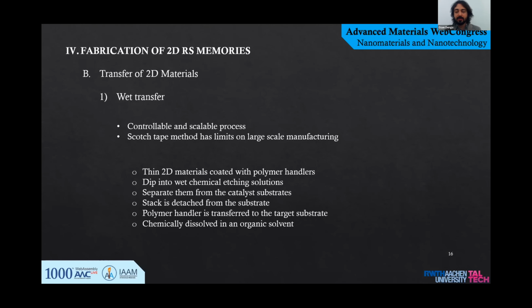But during the wet transfer process, thin 2D materials coated with polymer handlers are dipped into wet chemical etching solutions to separate them from the catalyst substrates. Then, the polymer and 2D material stack is detached from the substrate. And the polymer handler is transferred to the target substrate, where it is chemically dissolved in an organic solvent.